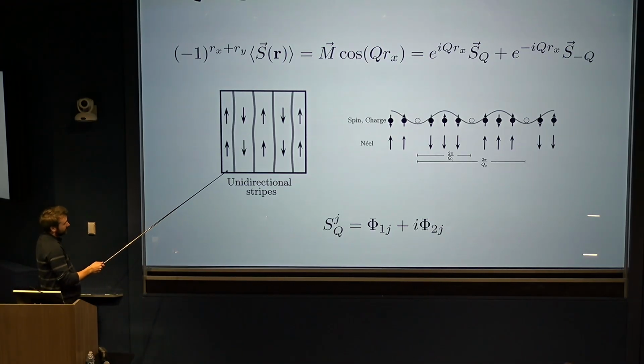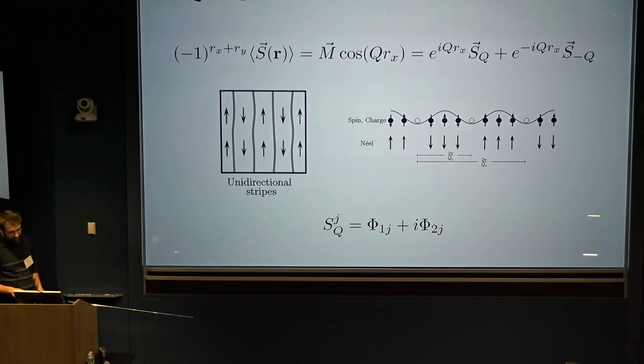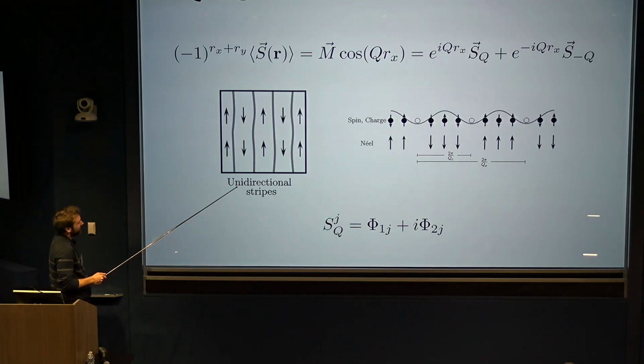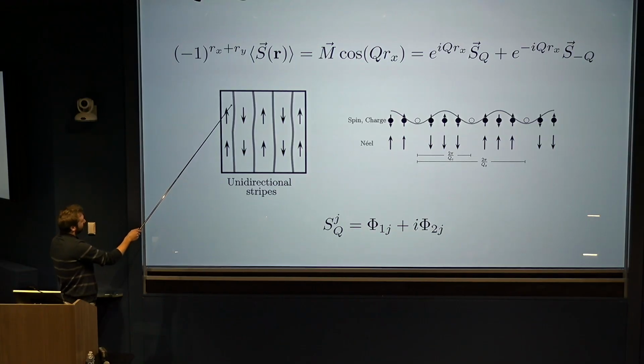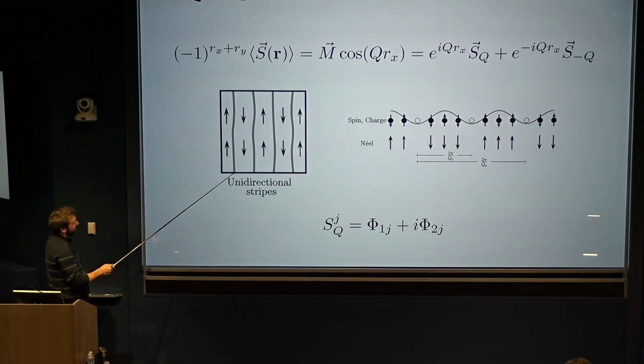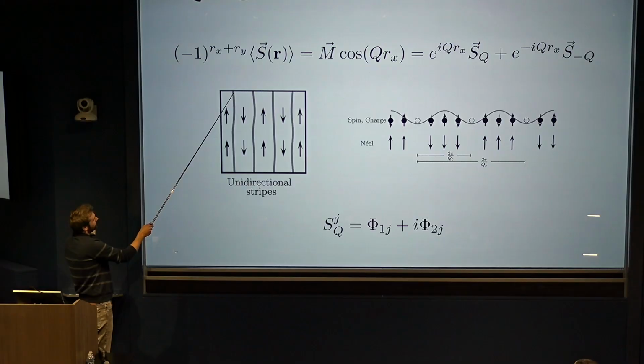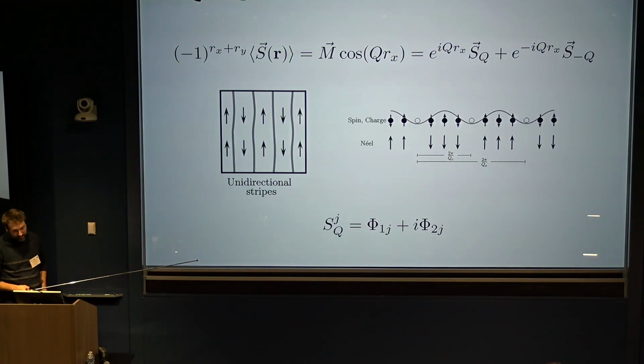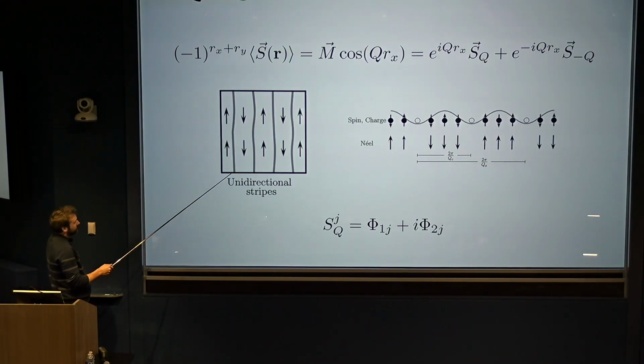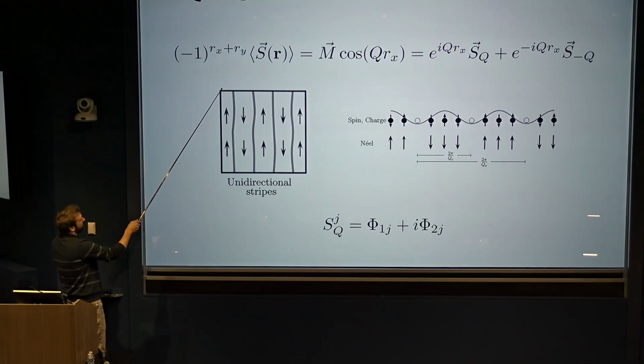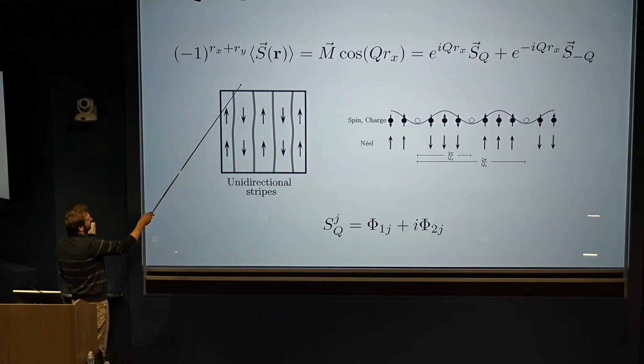And so it's also known that whenever you have this sort of spin density wave order, there's also unavoidably a charge density wave order associated with it. And in particular, what you find is that along these gray lines here, where the antiferromagnetic order or the Néel order goes to 0, that's where you accumulate charge. And in the context of the cuprates, this is where you actually accumulate holes. So you get a dip in the charge density whenever you cross these two regions with antiferromagnetic order.